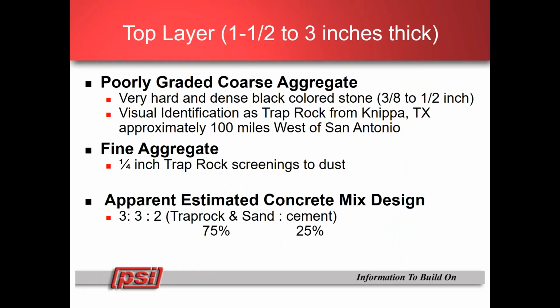The surface aggregate was a very hard, dense, black-colored stone, 3/8 inch to 1/2 inch, and it was visually identified as trap rock originating from Knippa, Texas, again, approximately 100 miles west of San Antonio. The fine aggregate in this material was the 1/4 inch trap rock screenings to dust, and there might have been some field sand that was used in that mix as well.